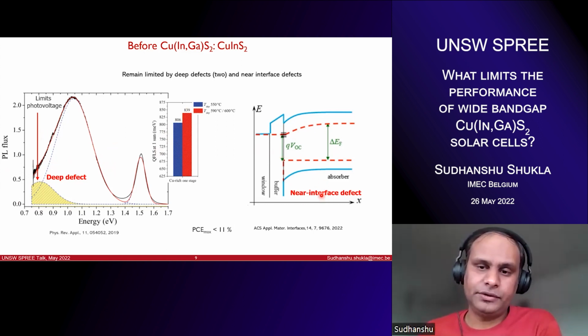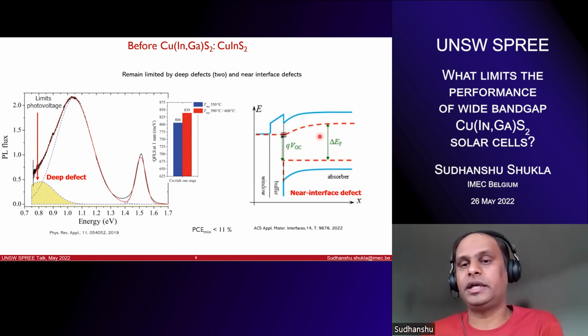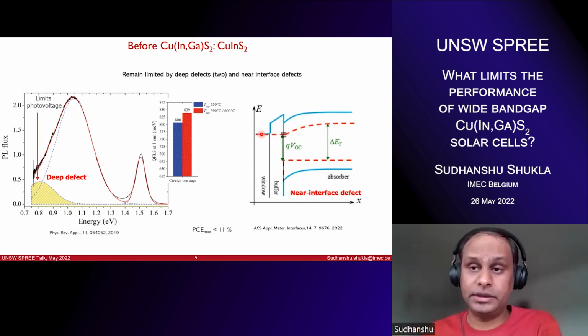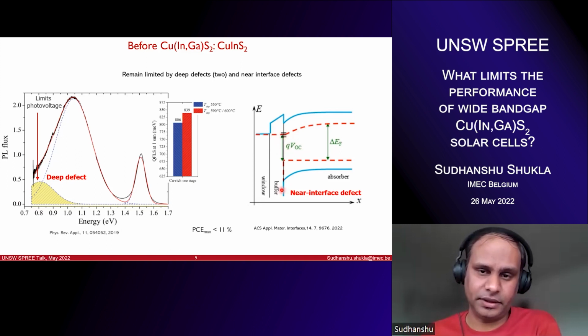And the other thing we have shown recently is that you have near interface defects at the CIS, and no matter what buffer you use, cadmium sulfide, even if you use the one that has this spike type configuration, which is the desired one, you still get interface recombination. And the reason is that you have these near interface defects which are causing you the trouble.